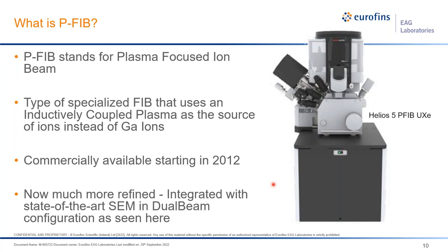So today we'll be focusing on the xenon variant of P-FIB, or plasma FIB. And this is essentially a tool that, instead of using gallium, uses an inductively coupled plasma as the source of ions, instead of the gallium LMIS. And although P-FIB has been commercially available since 2012, current dual beam configurations now combine a state-of-the-art SEM with the P-FIB column, which really is enabling a wider range of potential analyses. And while a variety of gases are available, such as argon and oxygen and nitrogen, today we're going to focus on xenon specifically.